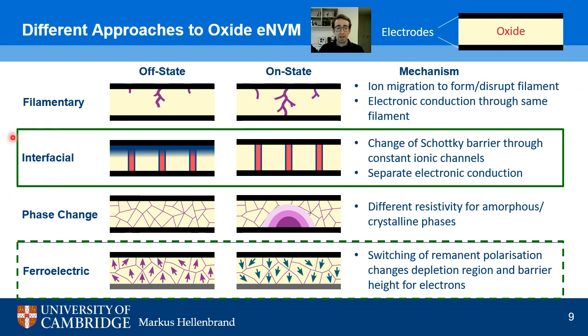So the one that I explained is encased here in green. It would be called interfacial switching, because as I explained, the interface between one electrode and the oxide is critical for realizing the resistance state. In order to control the resistance state, we have these channels. So remember, we combine different materials, one with good conduction of oxygen vacancies and one with good electronic conduction.